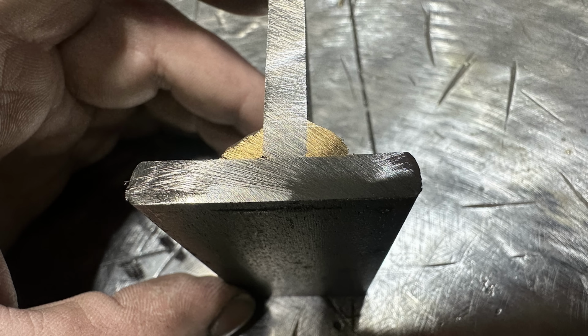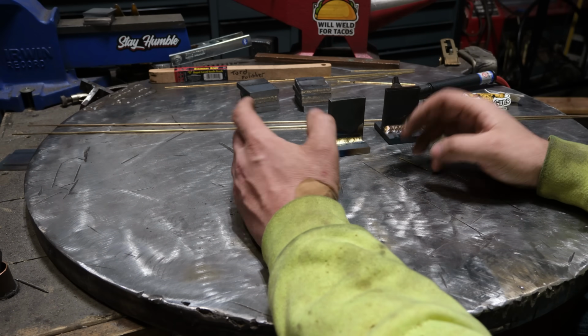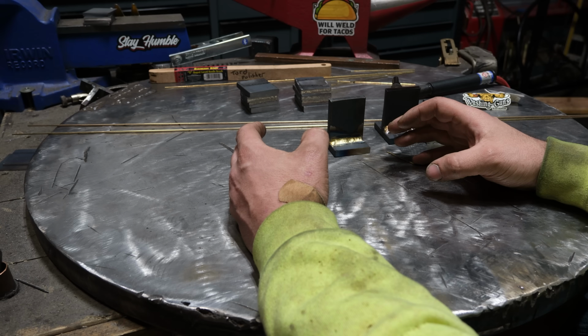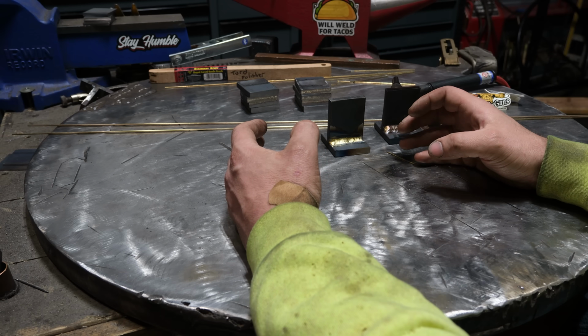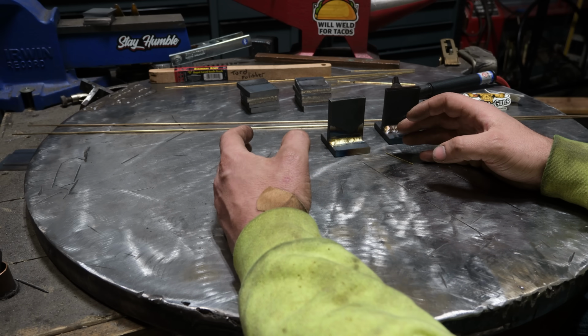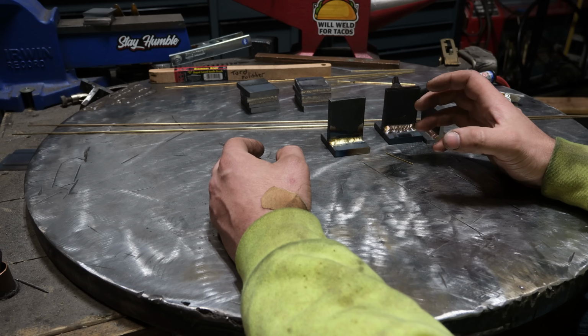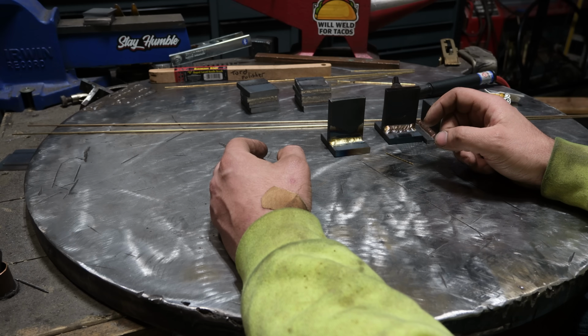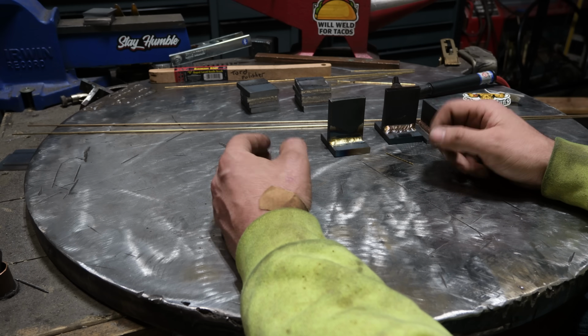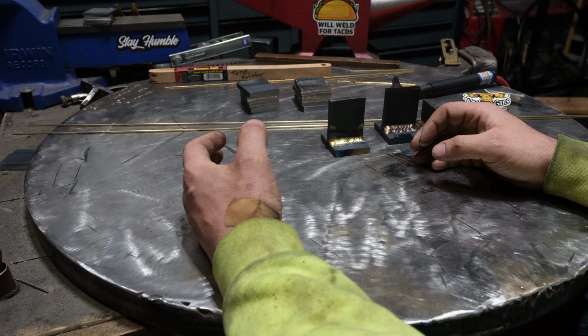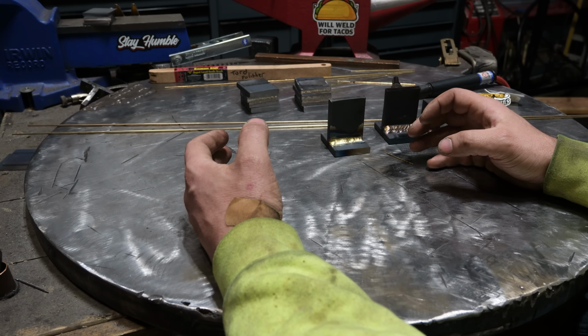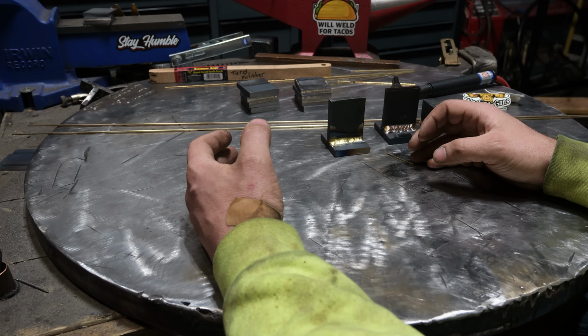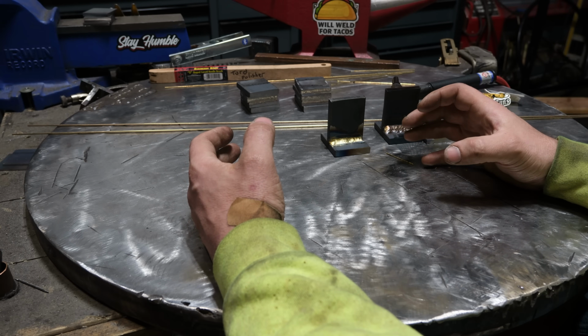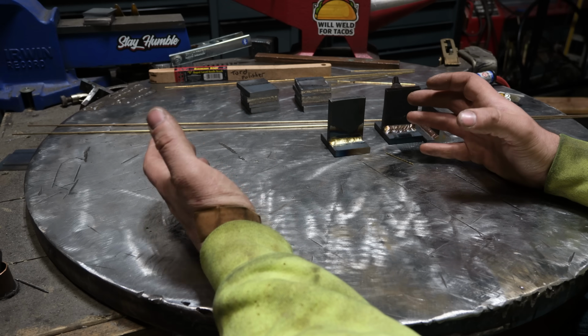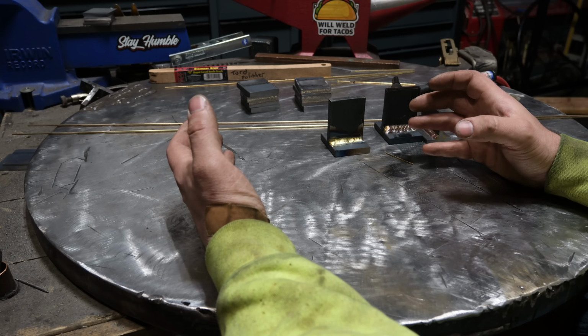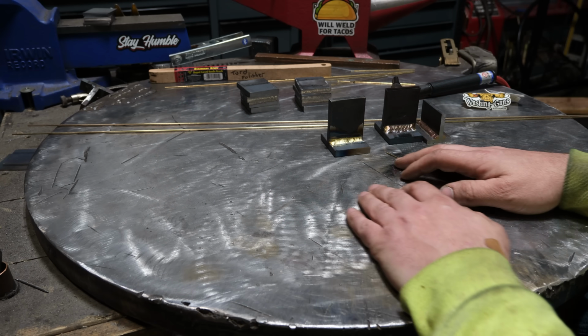Let's move on. So as you guys saw, the braze more or less just sits on the plate, and you're not going to get penetration, and penetration is not desirable. You really don't want the base material to mix with the braze alloy, because realistically it's probably going to create voids, defects, or strength related issues. So ideally you should have zero penetration, and it should sit more like a glue or a bead of caulk and not like a weld.